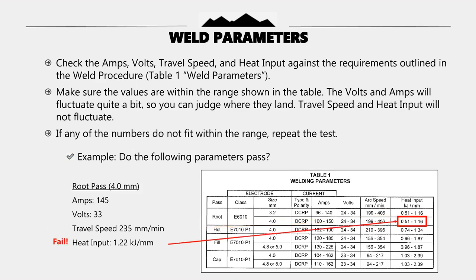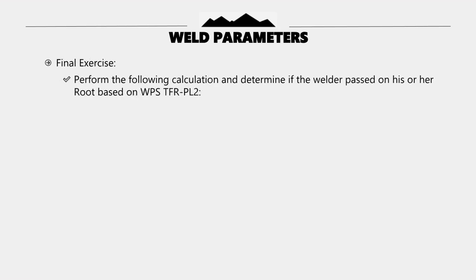Lastly, look under the heat input column on the line next to root pass and 4.0 mm rod size. The range shown is 0.51 to 1.16. Since our heat input of 1.22 kilojoules per millimeter falls outside this range, it does not pass. Even though the weld passed the amps, volts, and travel speed, it did not pass the heat input. Therefore the weld fails.